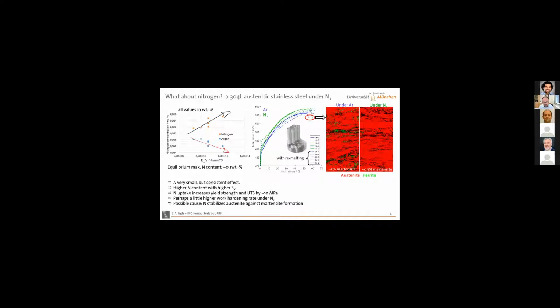And also, if you look at tensile tests in the middle, yes, there's a tiny difference, but I really had to magnify this axis quite a lot to make it visible. So we think that the main difference is that the little addition of nitrogen in this case adds a bit of austenite stability, which you can see after deformation, where you have less strain-induced martensite. So chromium, although it is a nitride-forming element, apparently is not enough to show a big, remarkable effect when processed under nitrogen.